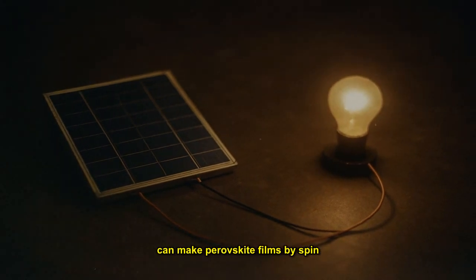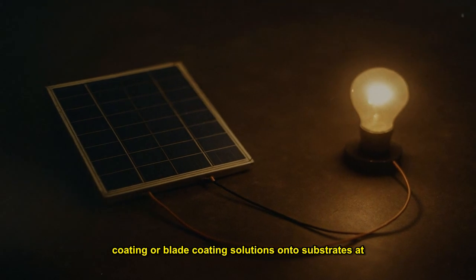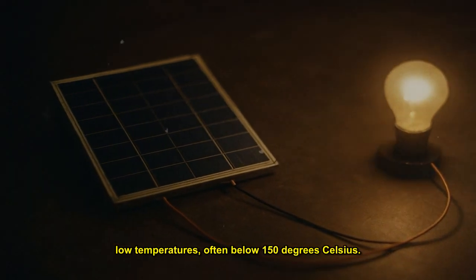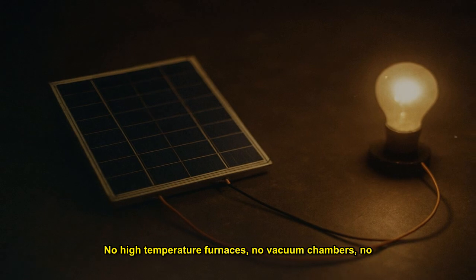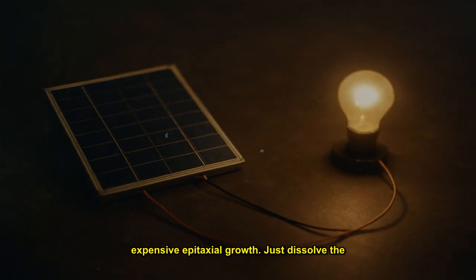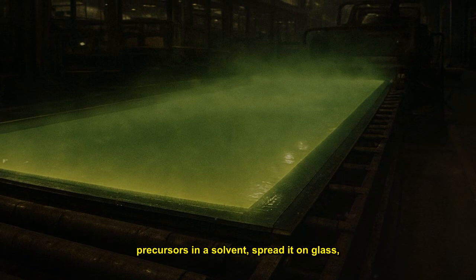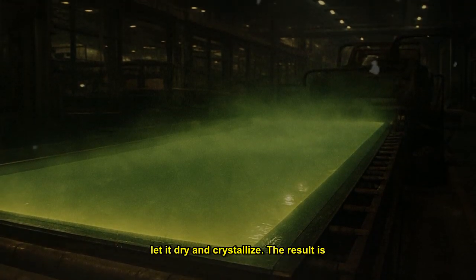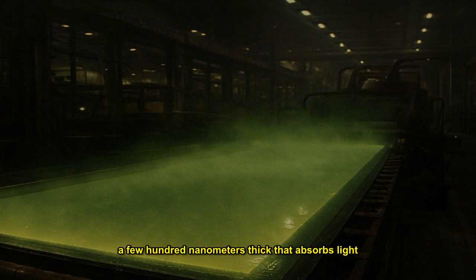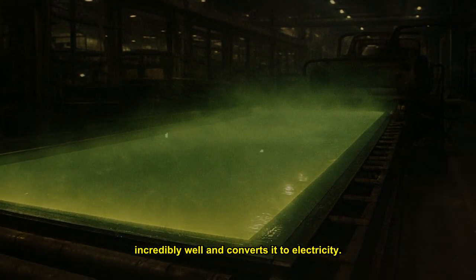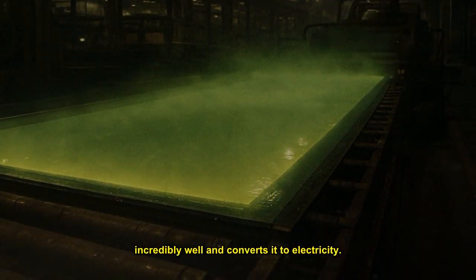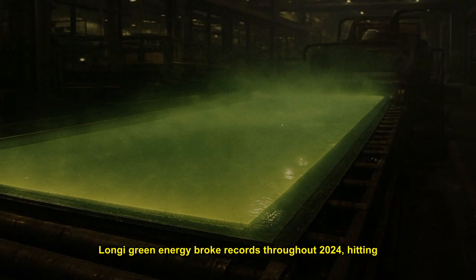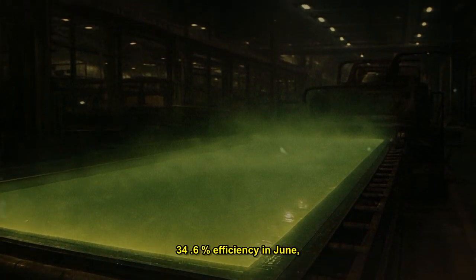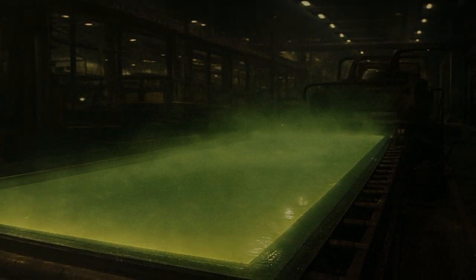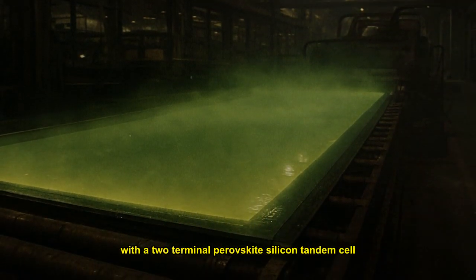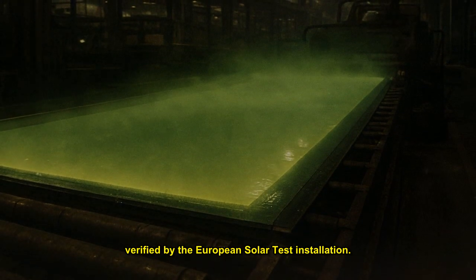Manufacturing is shockingly simple compared to silicon. You can make perovskite films by spin coating or blade coating solutions onto substrates at low temperatures, often below 150 degrees Celsius. No high temperature furnaces, no vacuum chambers, no expensive epitaxial growth. Just dissolve the precursors in a solvent, spread it on glass, let it dry and crystallize. The result is a thin film a few hundred nanometers thick that absorbs light incredibly well and converts it to electricity. LONGi Green Energy broke records throughout 2024, hitting 34.6% efficiency in June with a 2-terminal perovskite silicon tandem cell verified by the European Solar Test Installation.